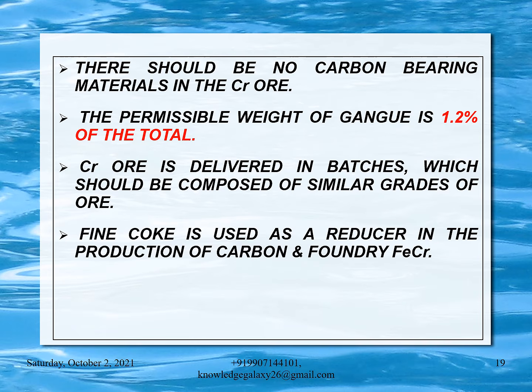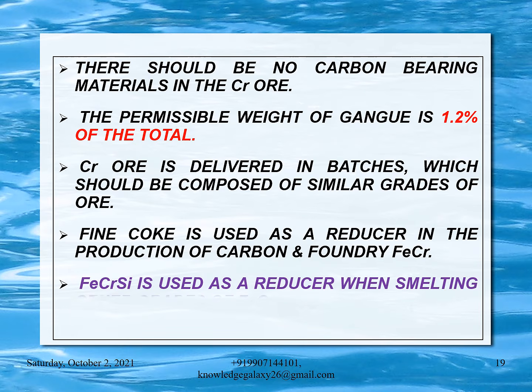Fine coke is used as a reducer in the production of carbon and foundry ferrochrome. Ferrochrome silicon is used as a reducer when smelting other grades of ferrochrome. There is a difference of reducers used for different grades of ferrochrome, so please do remember.